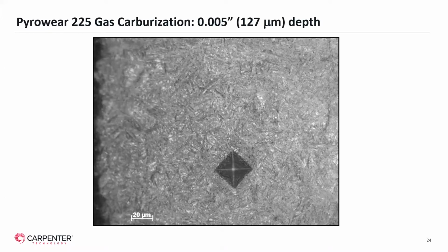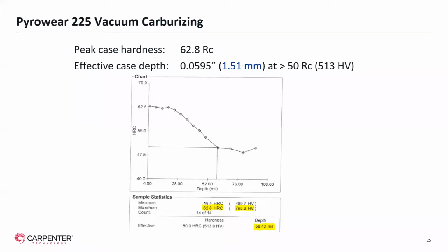This is a typical microstructure after gas carburizing. That Vickers indentation was taken at 5 thousandths depth or 127 microns depth. The surface is given on the far left side of this micrograph. Microstructure looks very good. We've also vacuum carburized Pyrowear 225, and we've got similar results. A peak hardness in the case of about 62.8 Rockwell C, and an effective case depth, again, of about 1.5 millimeters or roughly 60 thousandths depth.